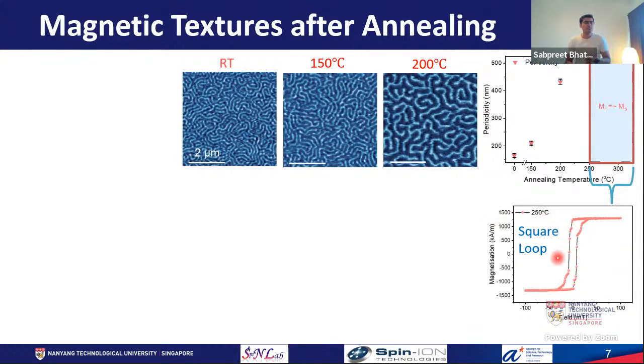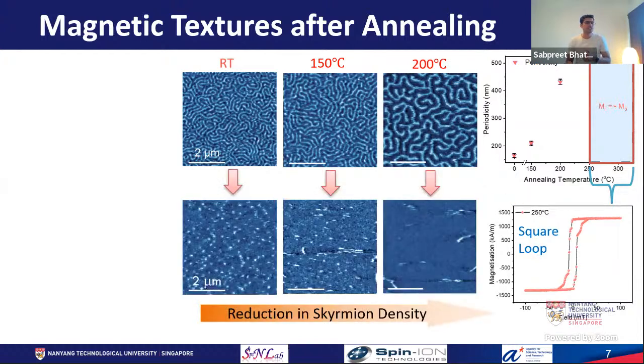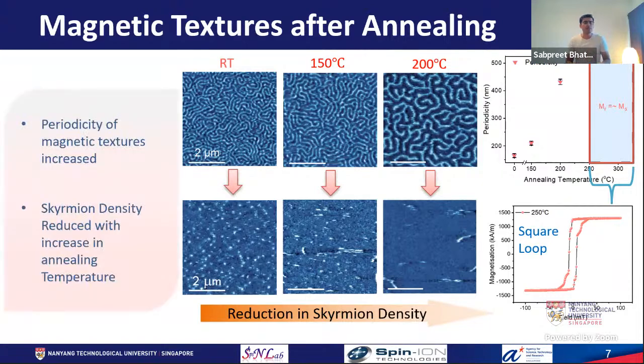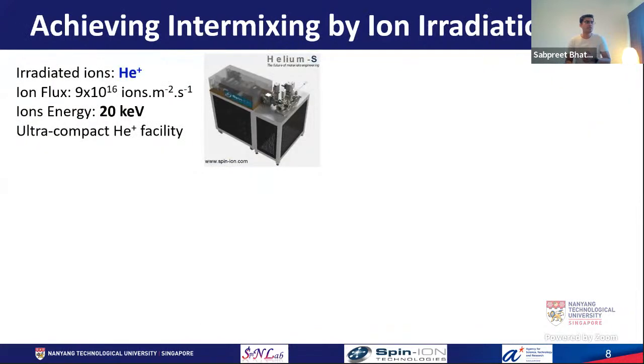Now, if for these samples we increase the magnetic field and image the textures, we saw that the skyrmion density has been reduced with increase of the annealing temperature. From here, we can say that annealing is not a viable method to increase the skyrmion density. So we move to our next method, which is helium ion irradiation. So the helium ion irradiation was done by using an ultra compact helium facility. We have used an ion energy of 20 kilo electron volts.